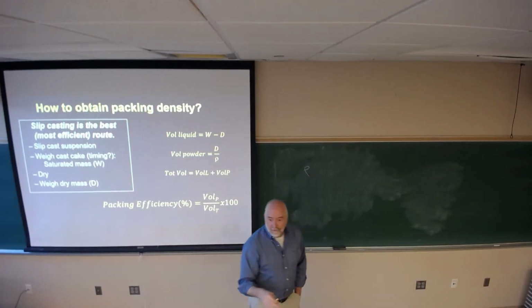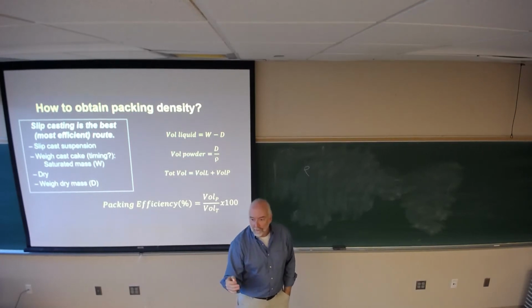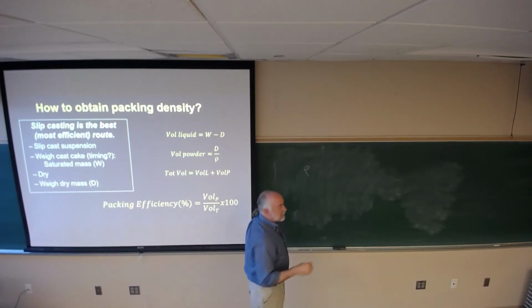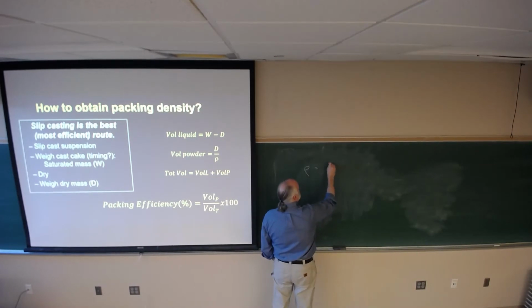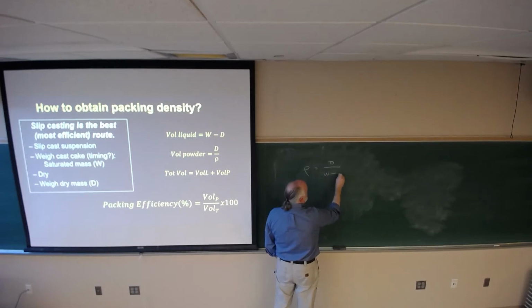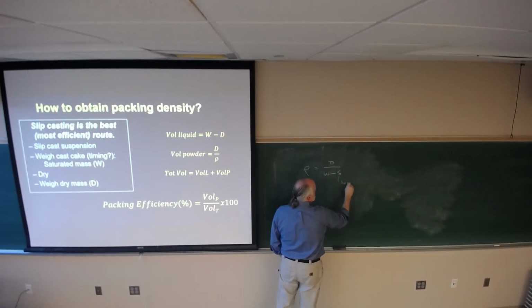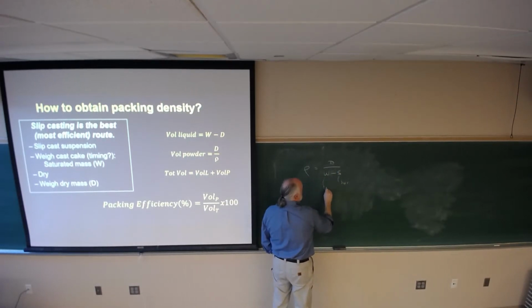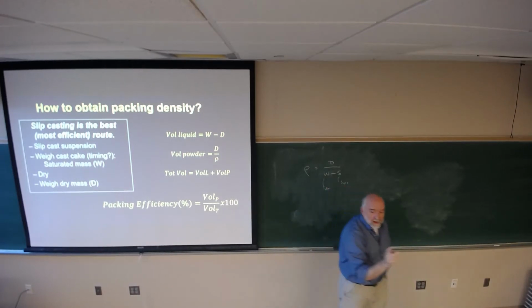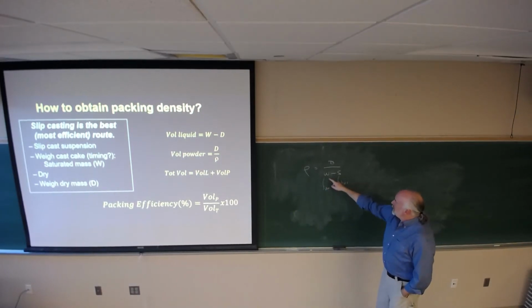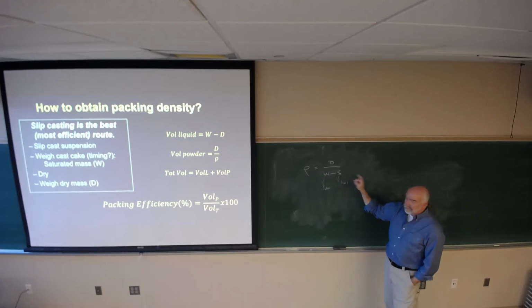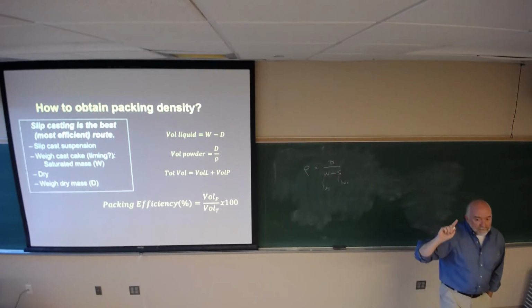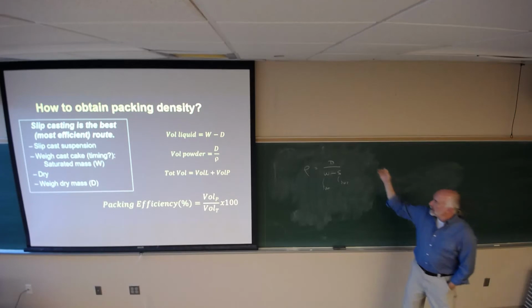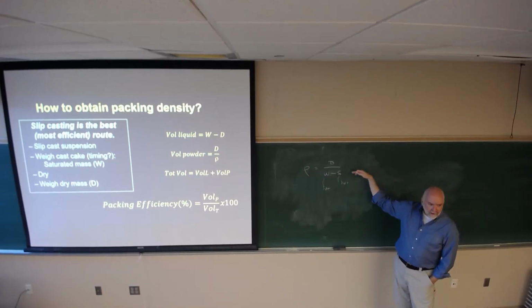Archimedes is measuring the volume of water overflowing a bathtub. We're not measuring the volume of water, we're doing a mass. The density of the system is the dry mass divided by the saturated mass, designated by W, minus the suspended mass. The saturated mass minus the suspended mass is the volume of the sample. So I get my dry mass divided by the volume, which gives me density.